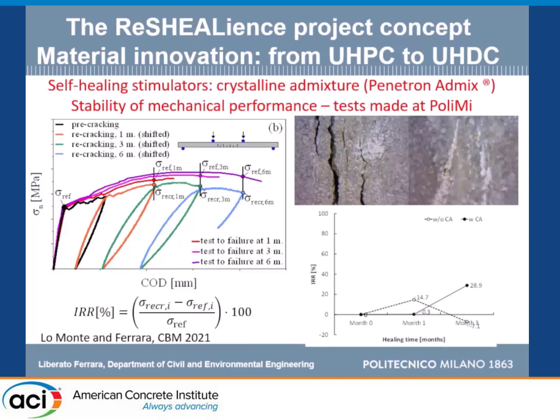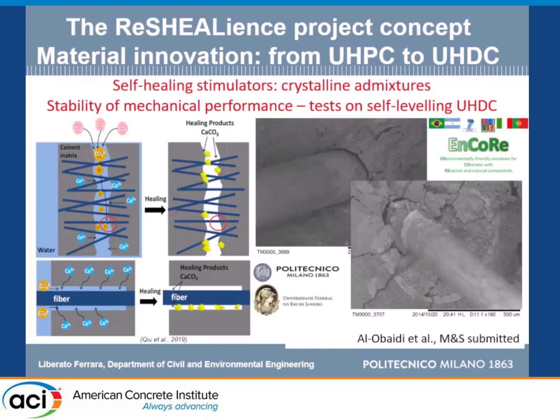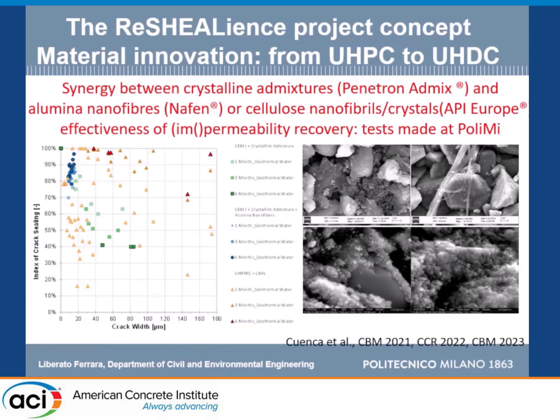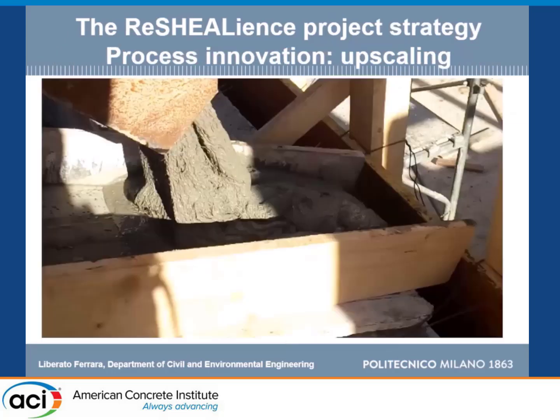This crack was completely closed, and not only did the performance over time stay constant, the material performance and the structural performance. We performed some microscopic investigation also to understand the reasons of this, and we also boosted it through the use of nanotechnology. You can see these data points here, in which we used alumina nanofibers. We were able to keep the opening of the single crack below tens of microns, which are really very narrow, no hamper for durability.